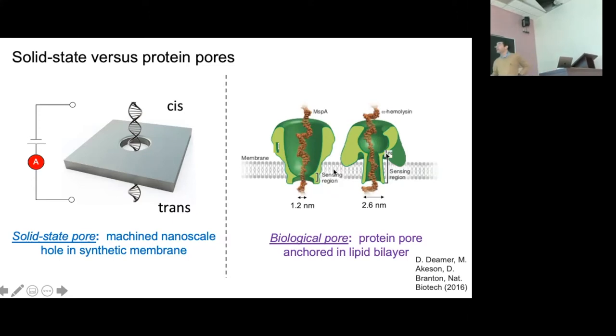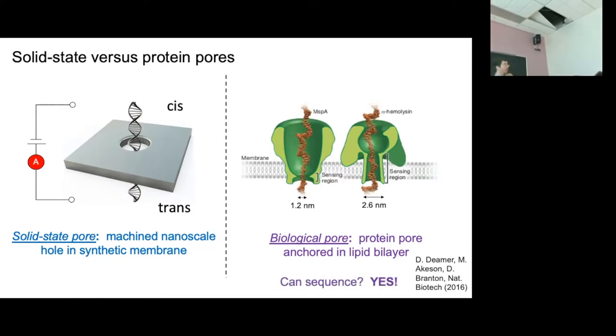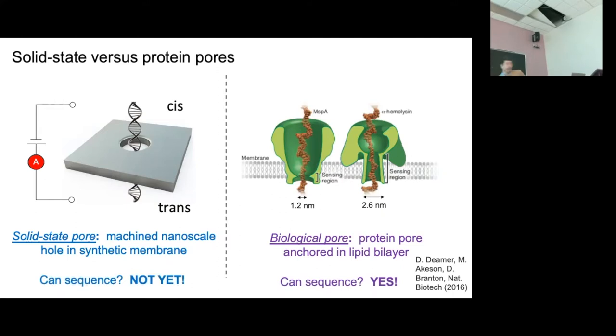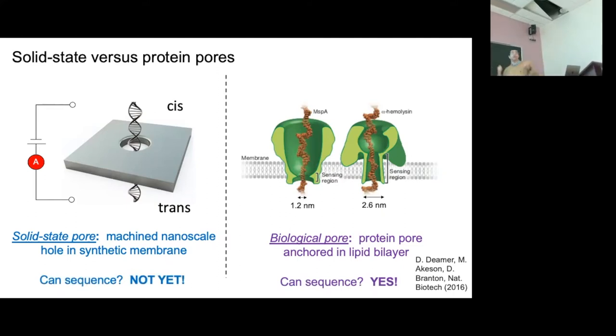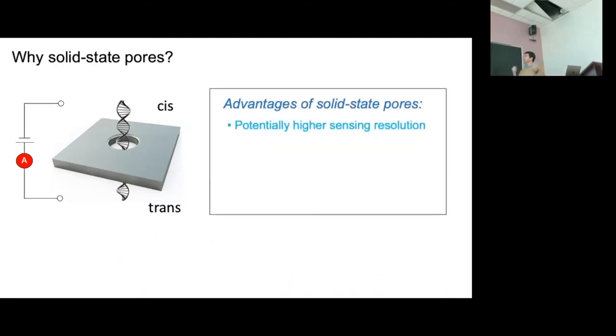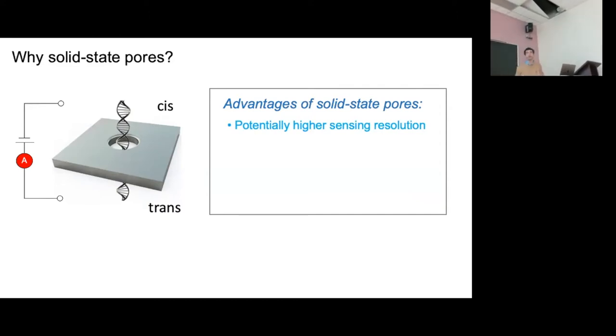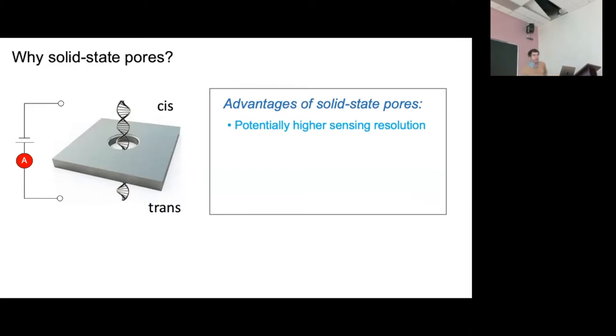Protein pores can sequence while solid-state pores cannot yet. You might wonder why the community is still interested in solid-state pores. The answer is potentially higher sensing resolution. In protein pores, even though the apertures are very small, they still get signals from about three to five nucleotides at once — they don't truly have single nucleotide resolution. There's a hope of using two-dimensional nanomaterials to create a pore with real single nucleotide resolution.